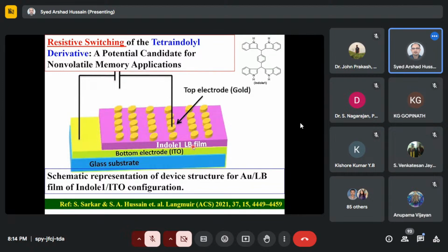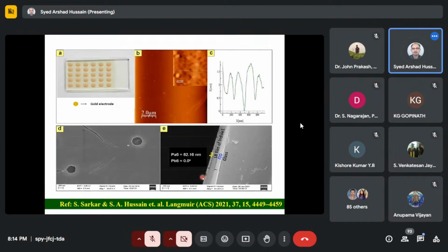So we designed this device using spin coating, the LB technique, and drop casting also. And we found that each technique has some contribution to the performance of that device. Okay. So this is the surface of the device after depositions, and this is the cross-section of the device, the cross-sectional image. This is the LB film, thickness say 80 nanometer or something like that.